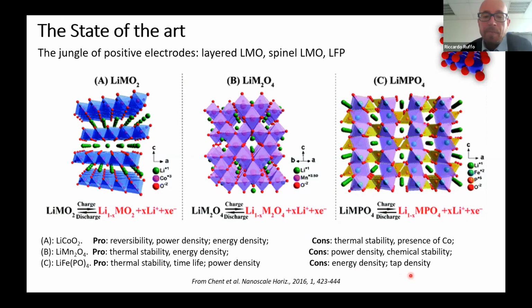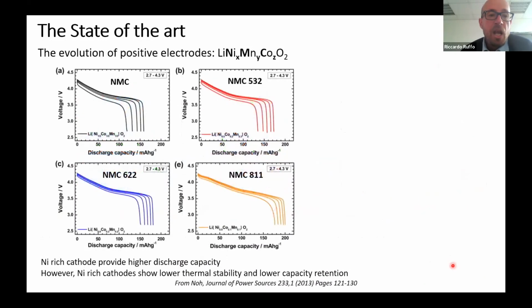And also another point, which is less considered, is the tap density, because in the case of oxides, we can store much more material in the same volume, while in the case of phosphate, the tap density is such that we cannot have very good energy applications for that. So in the evolution of the positive electrodes, we are using now a layered oxide, which is a mixture of nickel, manganese, and cobalt, like 1:1:1, like in this case.